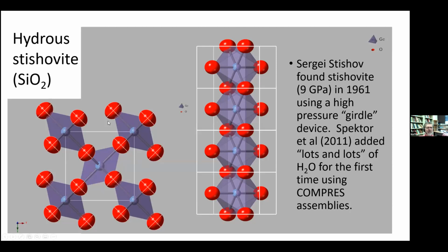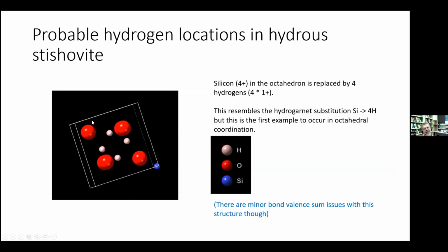You know, there's really no room. This is a stishovite structure, and there's no room. It's a rutile structure, edge sharing octahedra, very small spaces in between. So where would the water be? But eventually we figured out that it was a silicon vacancy with four OHs on it. And it was basically like a hydrogarnet substitution, but 6 oxygens instead of 4.